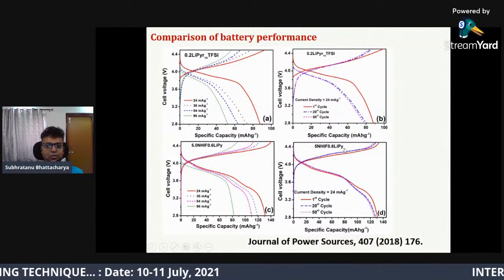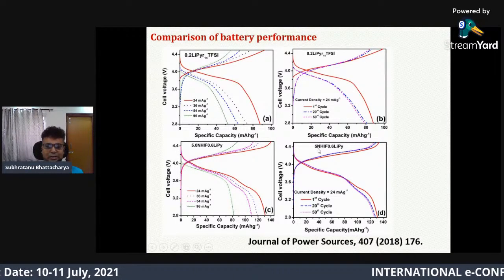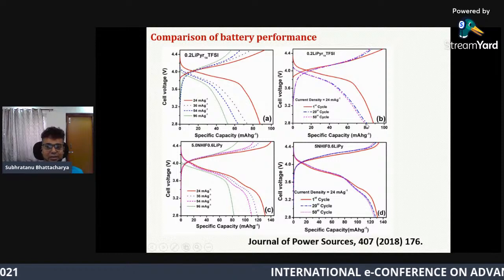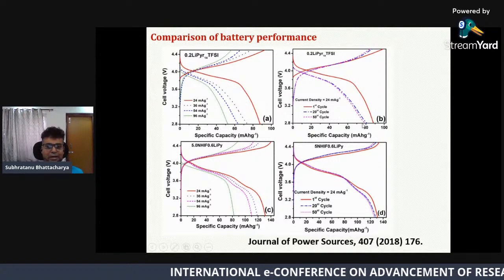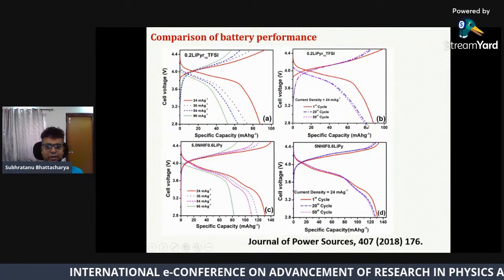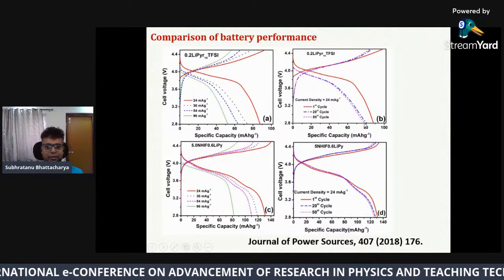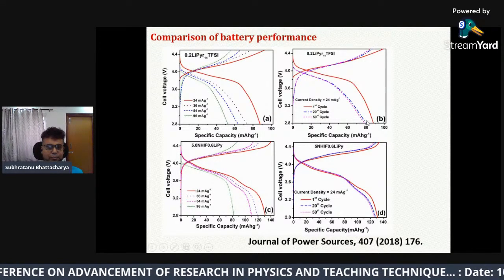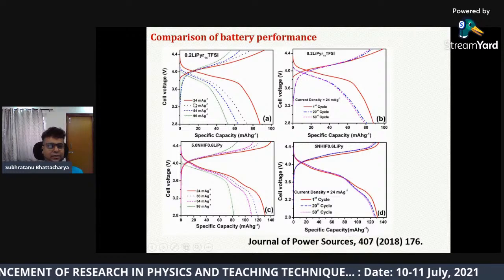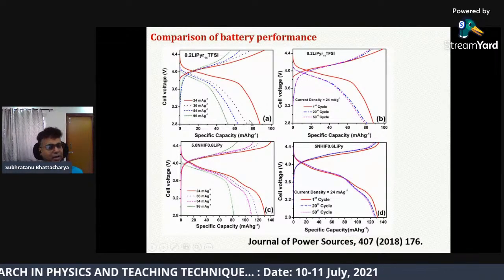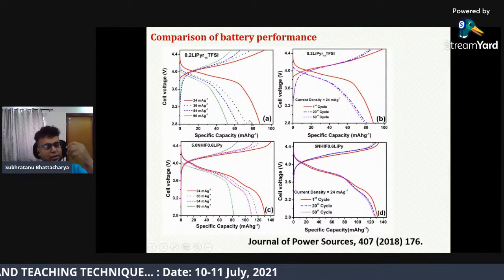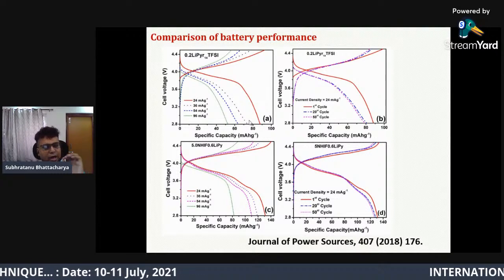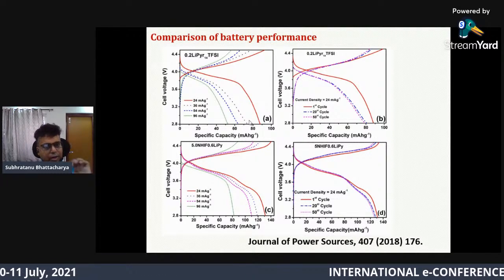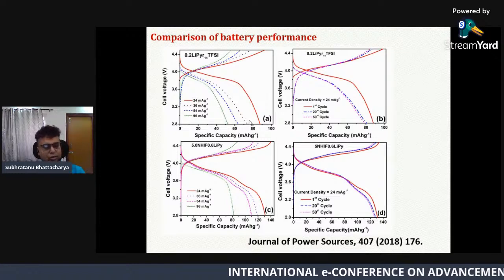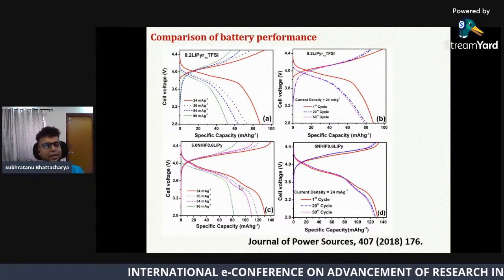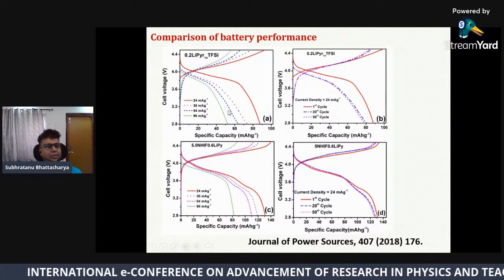Whereas if we use ionic liquid based electrolytes, you can see there is capacity fading also. By the 20th cycle it comes to 80, and in the 50th cycle it's less than 80 for the ionic liquid. And if you increase current, you can see there is capacity fading. It always happens because you are not moving 100% of the ions from cathode to anode and anode to cathode. That's why at high discharge current, you are getting capacity fading.